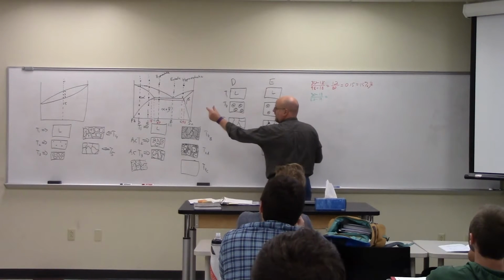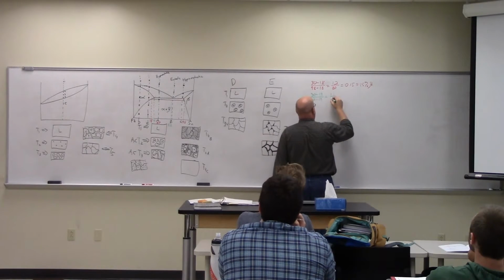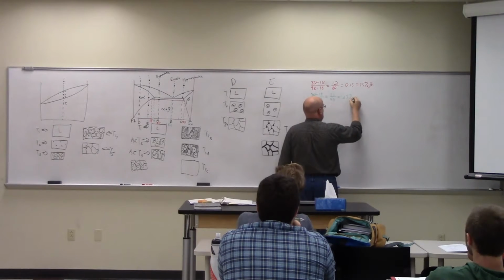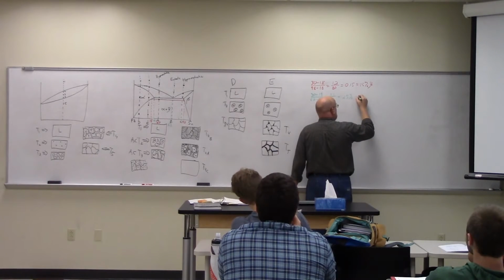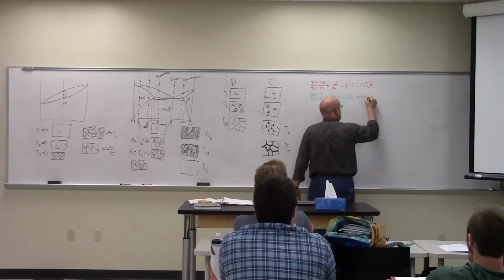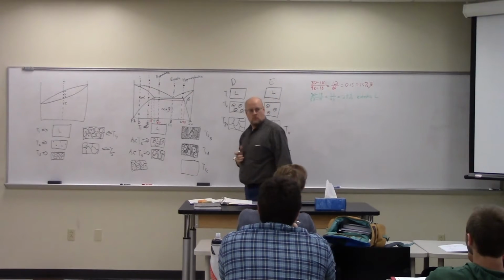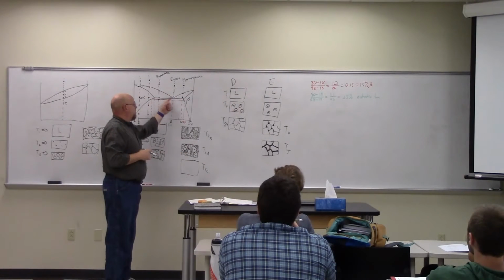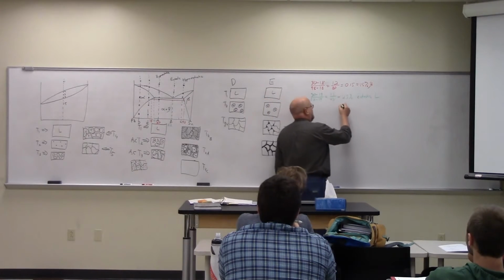That's the left-hand side. So that's 11 divided by 43, which is, let's just say 25%, I'm approximating, 25% eutectic liquid, right? This thing here is 25% eutectic liquid, and the other 75% then